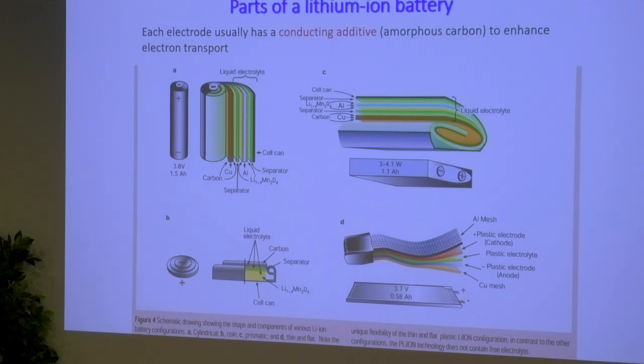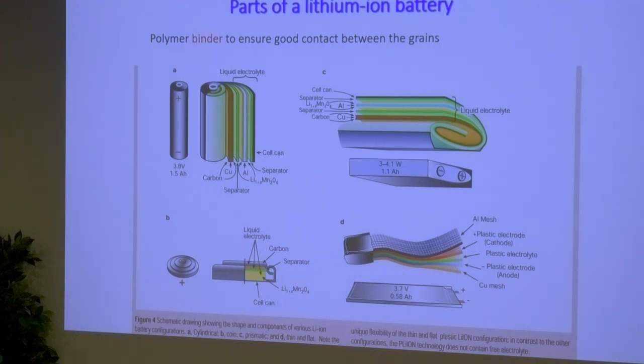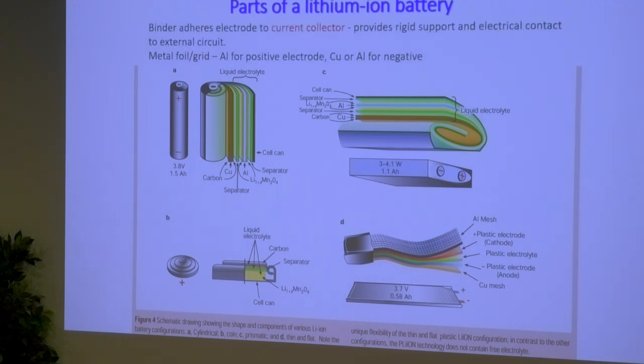Most of our electrode materials are not electronically conducting enough. So we add a conducting additive, typically an amorphous carbon, just to make them more conducting. We've got powders for our electrode materials, so we need something to stick them all together. So we have a polymer binder to ensure that we've got good contact between the grains. And the binder also sticks the electrode materials to what's called the current collector, which provides a form of rigid support and it provides electrical contact to the external circuit.